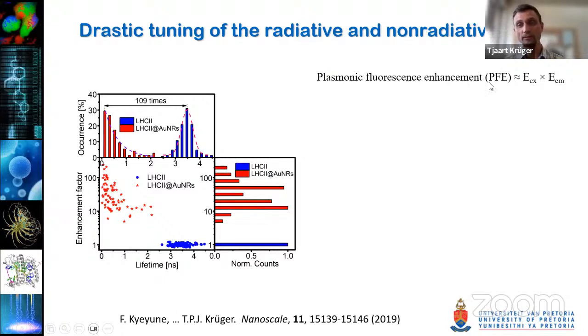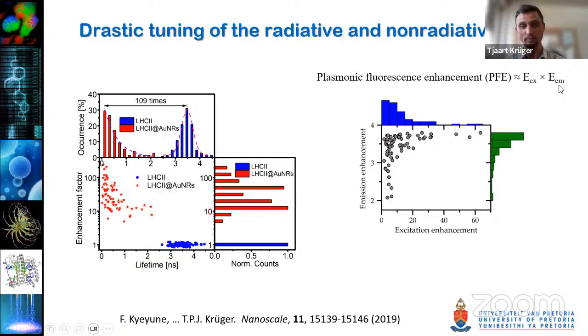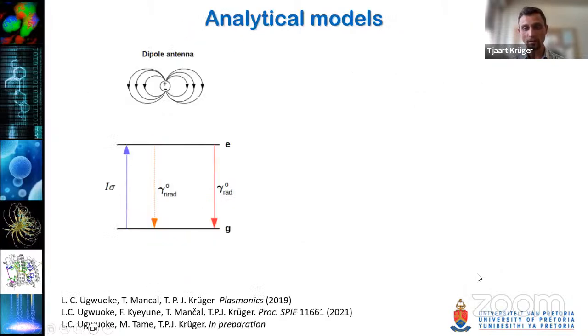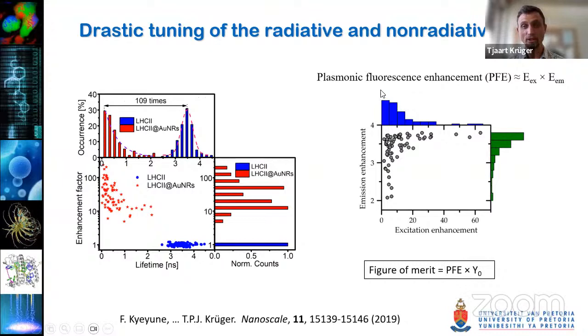So now the plasmonic fluorescence enhancement factor is, more or less, approximately a product between excitation enhancement and emission enhancement. Okay, and one can decouple these two in order to get for our enhancement, the amount of emission enhancement versus excitation enhancement. So most of the enhancement is excitation enhancement due to the concentration of the light in hotspots near the surface of the metallic nanoparticle. Okay, and one can also get a figure of merit. So if one starts with a very low intrinsic quantum yield, then one can in principle get a very large plasmon fluorescence enhancement in order to get a similar figure of merit when comparing different systems. So plasmonic fluorescence enhancement is especially very useful when one is working with a system that is having a very low intrinsic fluorescence quantum yield.